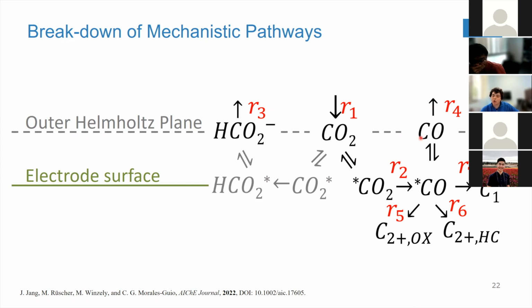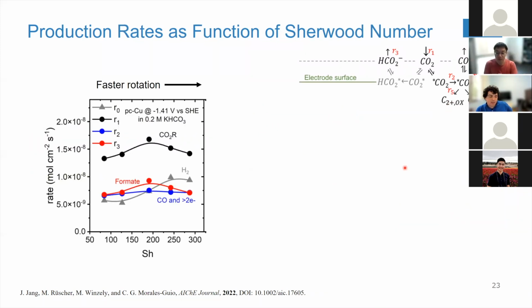So what we have done is different experiments, and quantified those different rates and how they depend on potential or on mass transport properties. Here on the left, we fix the applied potential. We do a lot of experiments under the same applied potential, and we simply change the Sherwood number. We change the rotation of the electrode, and we have a look at what happens. As we increase the Sherwood number, as we improve mass transport, the hydrogen evolution increases. The formate production rate also increases, hits a plateau and starts to decrease.